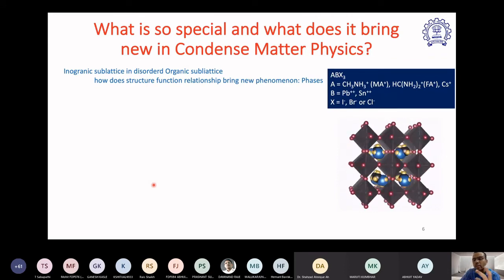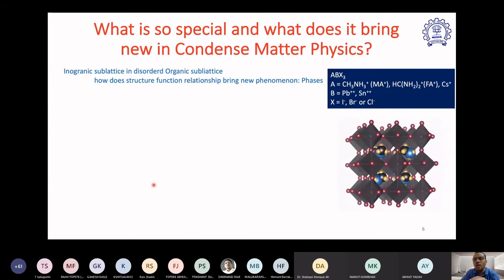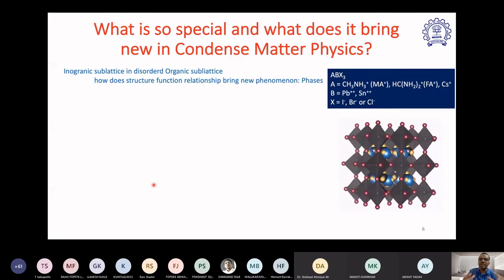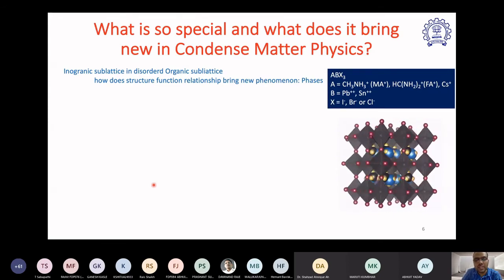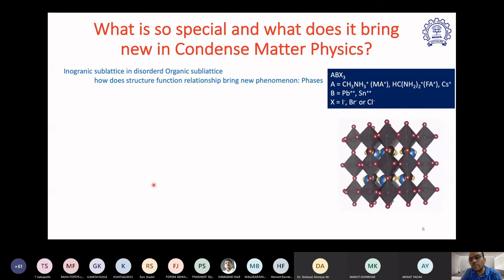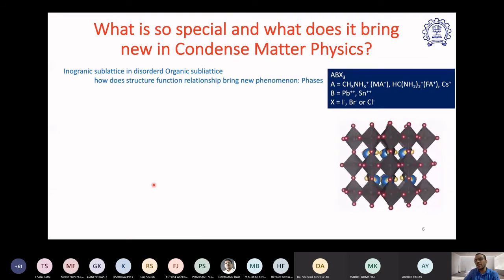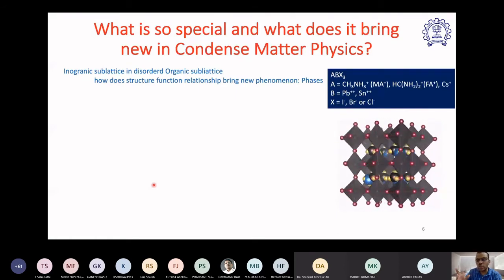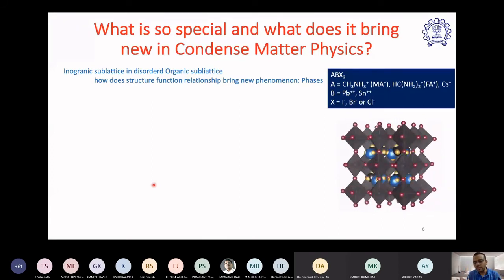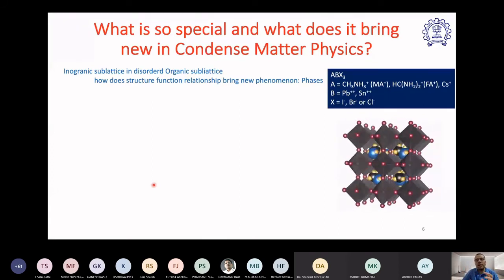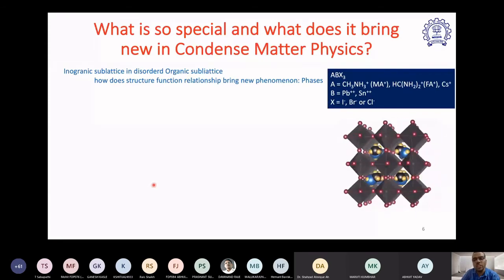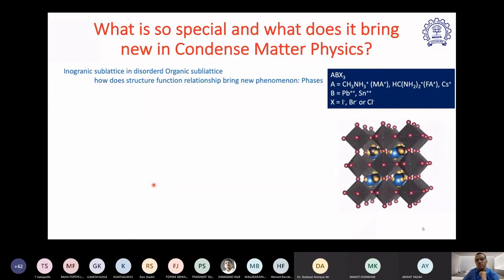It basically rotates around, it wiggles around, it can move here and there because there are enough openings. And the perovskite PbX6, which is an inorganic cage, maintains the structure. So you have an inorganic sublattice and a disordered organic sublattice. The methylammonium ion has its location fixed, but within that location, it's allowed to move around. So there's a disorder. When things are not fixed and are really moving, that means there's a disorder there. And how does the structure-function relationship bring new phenomena?